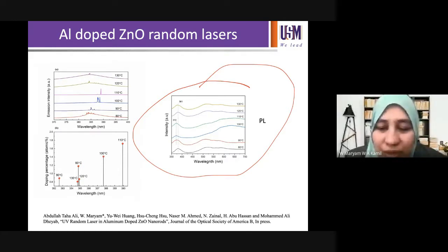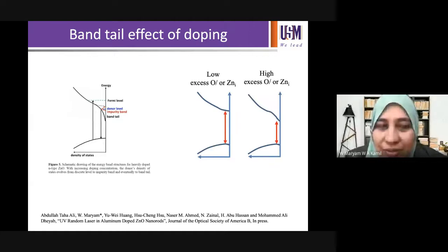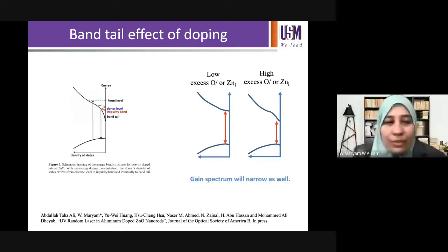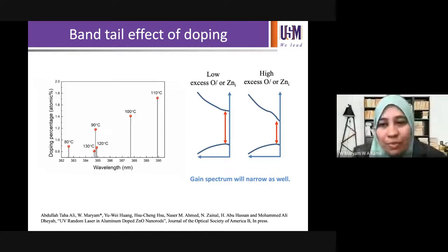when it is rich with oxygen interstitial. Okay, so we notice that when you have low excess of oxygen or zinc, this is the kind of band gap that you see. But as you increase that concentration, you actually see something called band tail effect. Now, the band tail effect of doping actually brings down this. So this is why we see the shift of wavelength in our random laser. Okay, so the gain spectrum is narrowing, and we are seeing the change in wavelength with increasing doping.